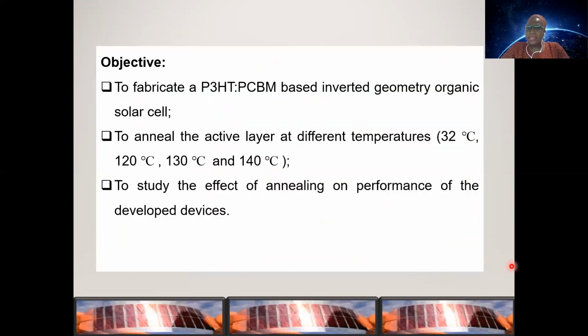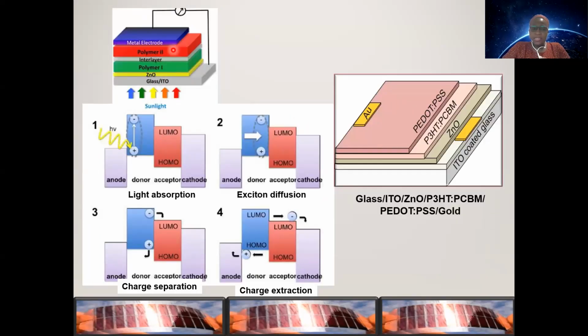So in this study, we fabricated the polymer blend of hexylthiophene and the butyric acid methyl ester polymer based on an inverted organic geometry, or inverted architecture. Then we annealed the active layer at different temperatures, and then we studied the effect of annealing on the performance of the device. Usually, the organic solar cells, the inverted geometry, has this structure or architecture. And the working principle is that sunlight or a light source falls on the cell, and then charges are separated, and you can actually use this separation of charges to power your device. So this is the framework that we adopted.